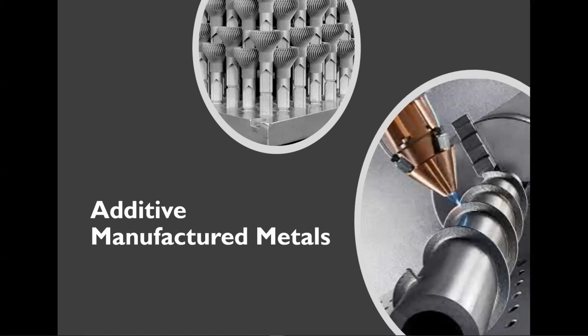And this has actually been theorized to be due to the creation of the aforementioned pores and defects throughout the material during the fabrication, caused by the layer by layer growth and the inherent defects associated with this process, and some thermal effects associated as well.